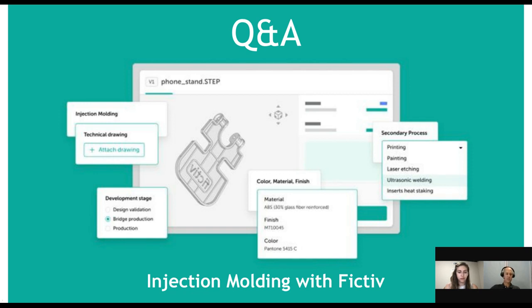You mentioned thickness. Thickness depends a little bit on the material. I always kind of gave a rule of thumb that, in inches, I like to see a part that's between 30 thousandths of an inch up to maybe 140 to 150 thousandths of an inch. There are some fillers that you can put into material to help give you thicker walls. But on average, I like to stay with that 30 to 150 thousandths of an inch thickness.